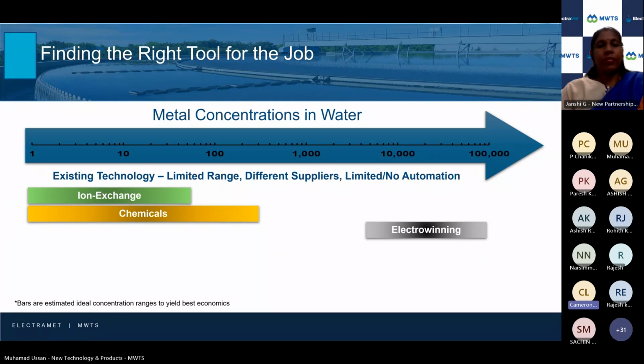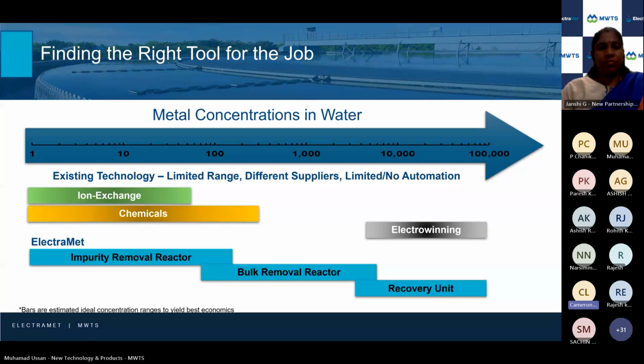And then you're looking at, what is the right tool for the right water quality? And this is where the existing solutions are suffering. You can see here in the green, ion exchange is very good for the CMP waste, but doesn't work for the concentrate stream. And electrowinning can process part of the concentrate, but it can't get down to discharge compliance. And there's a huge gap in the middle, around that 1,000 ppm range, where there's really no viable economic solution.